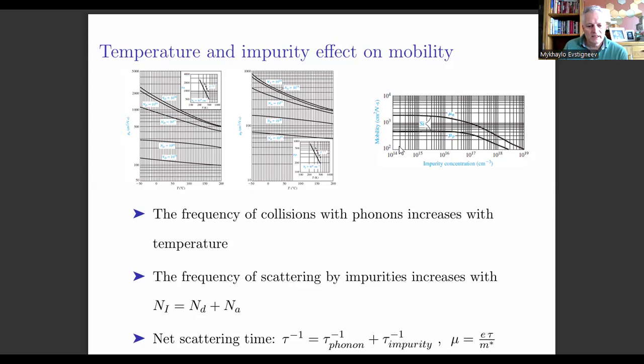So these plots show the mobility of electrons and holes in silicon as a function of temperature for different doping levels. And this plot shows the mobility as a function of the concentration of impurities, donors and acceptors, and donor plus acceptor, at room temperature, 300 kelvins. So we see that mobility decreases with impurity concentration and it decreases with temperature. Why? Because the frequency of collisions increases both with impurity concentration and with the temperature.